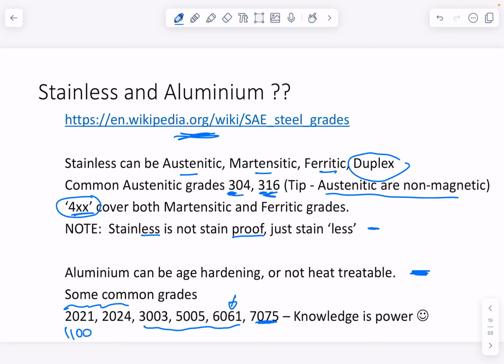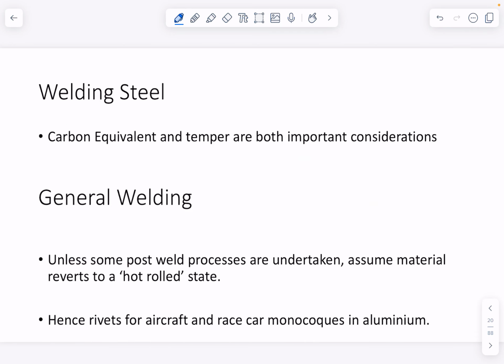So it can be challenging to weld, and that's why TIG is predominantly the thing to use with aluminium. You run an AC, alternating current, through the tip. Half the current pulls the oxide layer off. The other half of the cycle deposits metal down, if you like. It's worth just looking up some of the stuff if you're ever involved in it.